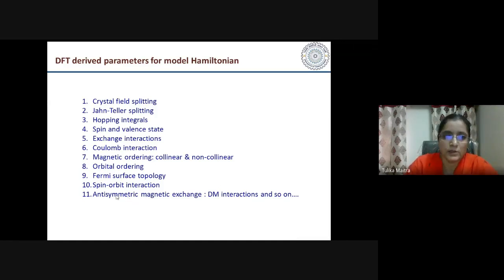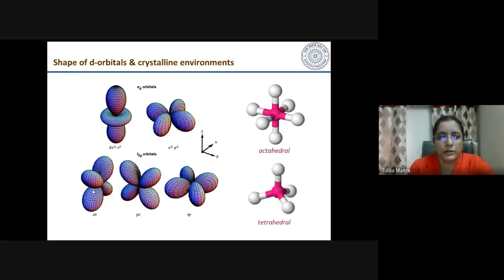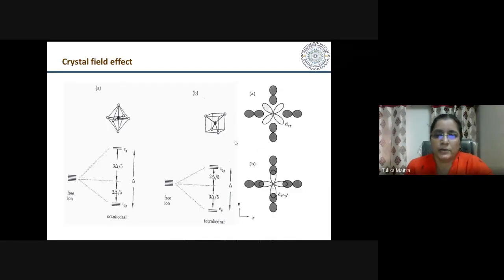Okay. So let me discuss a few of them. Suppose we are working with transition metal compounds, where the outer shell is the d shell. The orbitals have anisotropic shapes, as we all know. And when we put them in a crystalline environment, like for example an octahedral environment or a tetrahedral environment, we see that the energy levels split differently depending on the crystalline environment, because of the anisotropic nature of these d orbitals. Due to this anisotropic nature, the electrons feel more repulsion from the ligand ions or ligand orbitals in certain directions and less in certain directions.